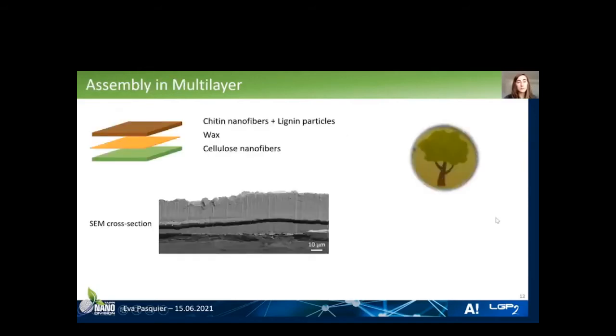And then we did some multi-layers. For that, we used cellulose nanofibers as a base layer, and then some wax particles, and then the chitin nanofibers and lignin particles on top. So this corresponds to the sandwich film for the wax, and we also replaced one of the CNF layers by chitin nanofibers and lignin particles. So you can see that the films look quite homogeneous.